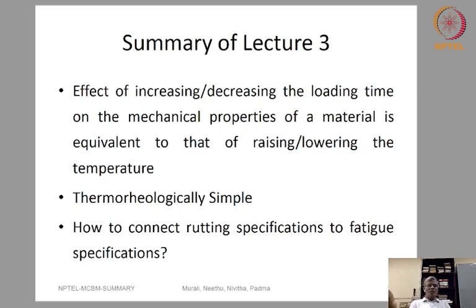If the response of the material is thermorheologically complex, you really cannot construct a master curve. What it means is, at 65 degrees centigrade, if the response of the material is predominantly that of a viscoelastic fluid showing a completely different relaxation spectrum, and at 15 degrees centigrade, if the response is predominantly that of a viscoelastic solid and shows a completely different relaxation spectrum, there is no way you can construct a master curve from 15 to 65 degrees centigrade using one single shift factor approach.